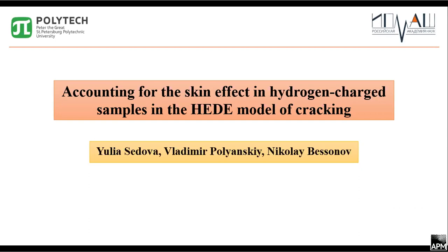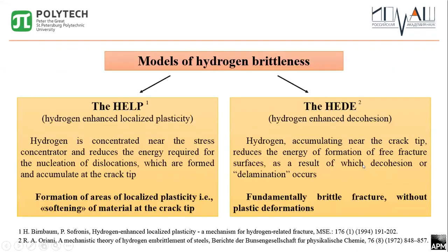significant effect of hydrogen on the material properties of some metals is acute at a much lower mass concentration, 100 thousandths of a percent. And even if its low concentration can be ensured during the production of alloys, the subsequent processing and operation of metal parts leads to an increase in hydrogen concentration, and it begins to significantly affect the properties of materials. One of the mechanical properties which is especially strongly influenced by hydrogen is crack resistance.